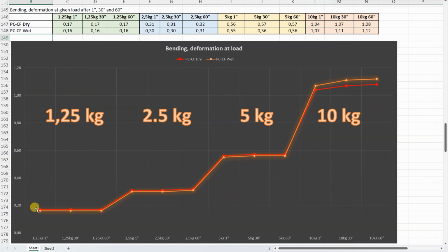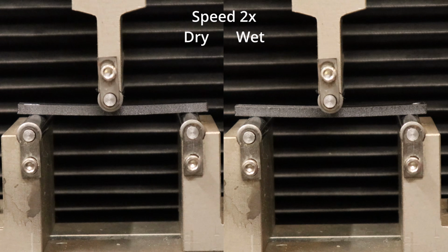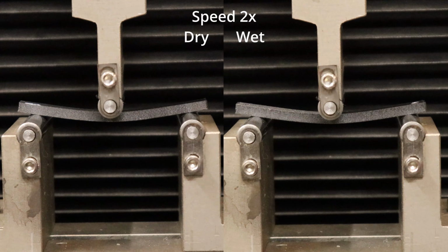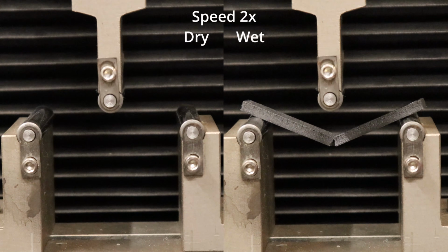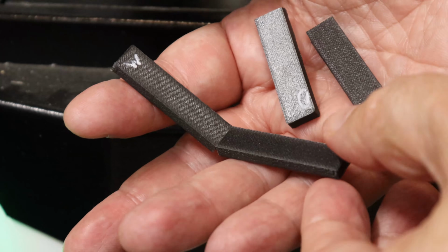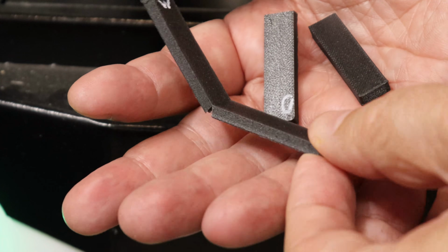This is an interesting one. We can see until 5 kilograms the deformation is very similar, but under 10 kilograms we can see more additional deformation on the objects printed from wet filament. Another 3-point bending test follows the ISO 178 standard. Even the break type was different.